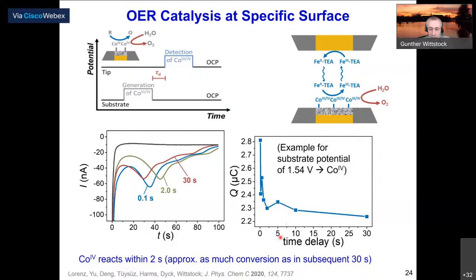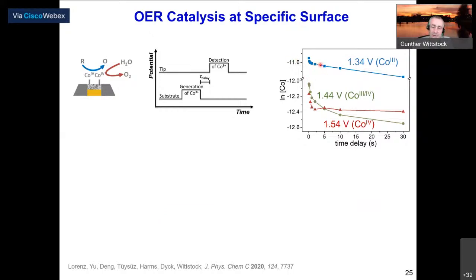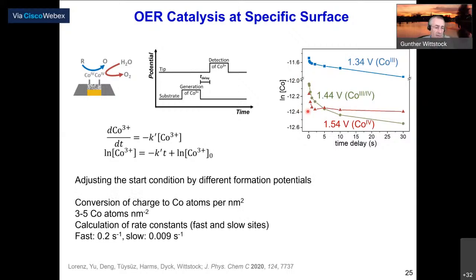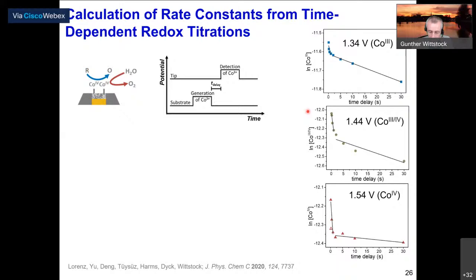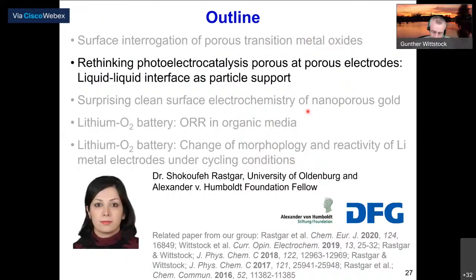So the charge was determined as a function of the delay time. And then we see that we have a very rapid decay within the first 2 seconds. That is the cobalt-4 species reacting away. And then we have a much slower conversion in the remaining 30 seconds. That can be, of course, analyzed in more detail here as a function of the potential to which the potential excursion was made to generate the cobalt oxides. And then you see if we have only the 1.34 volt and it's only cobalt-3, then we have mainly this decay. If we go to higher potential, we have this initial fast decay there before. That can be fitted. We can extract rate constants for the different sites on the cobalt atoms at the surface of that complex oxide. Okay, so here again, plotted in a logarithmic scale.